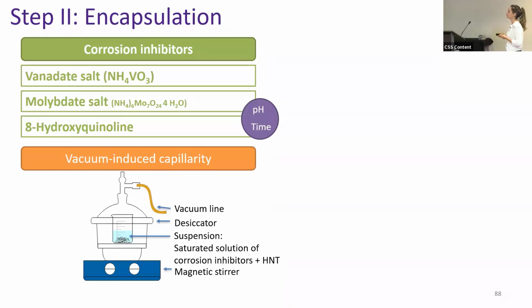So basically, we prepared a suspension of the nanotubes in a saturated solution of the corrosion inhibitors, and we placed it into a desiccator, connected to a vacuum pump, and vacuumed. So we remove all the air, and this forced the loading of the nanotubes.